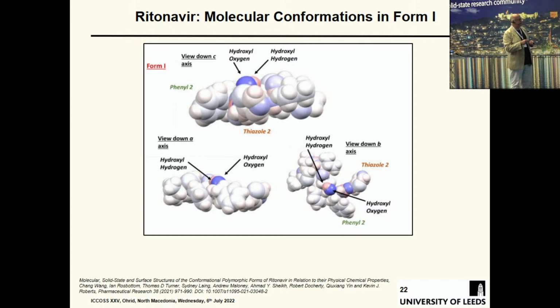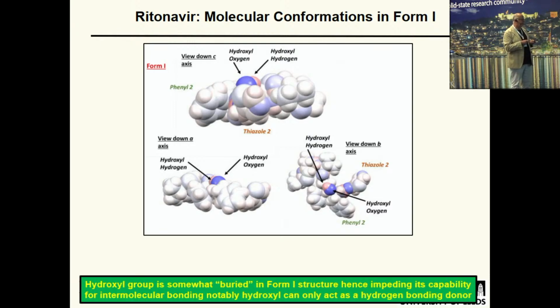And you can get an idea, still staying with the molecular agenda, from the conformations here in space-filling models, and you can see that a key thing is this hydroxyl group in the middle. And in form 1, the hydroxyl is only a hydrogen bond donor, because the oxygen is not so accessible to be an acceptor. And that's because of the conformation of the molecule. So the hydroxyl group is somewhat buried in the form 1 structure, impeding its capability. So the molecule is so big, even though it's got a good set of donors and acceptors, it's difficult to align those. It's a bit like aligning a spacecraft for docking.